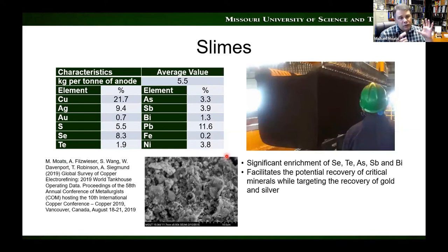So the anode dissolves. Some of the elements go into the electrolyte. Some stay solid and collect on the anode. So you can see the pretty copper anode has turned black. That's this powdery material. Some has sloughed off, fallen off, and entered the concrete cell at the bottom. If you look under a micrograph, it's just a hodgepodge of particles. Those particles have been well characterized over the years. We know all the phases that are there.